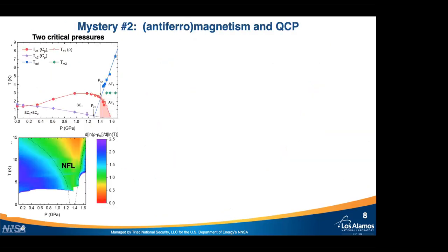So let me tell you about the phase diagram that we can construct with this. This is the temperature-pressure phase diagram. We can see again that at low pressures, the two superconducting transitions cross each other. One of them is enhanced, the other one is suppressed. It's interesting that we can assign two critical pressures. First, the critical pressure that is the extrapolation of the magnetically ordered state, PC1, and then the second one, PC2, where this extrapolation of what we think is magnetism meets the superconducting state.